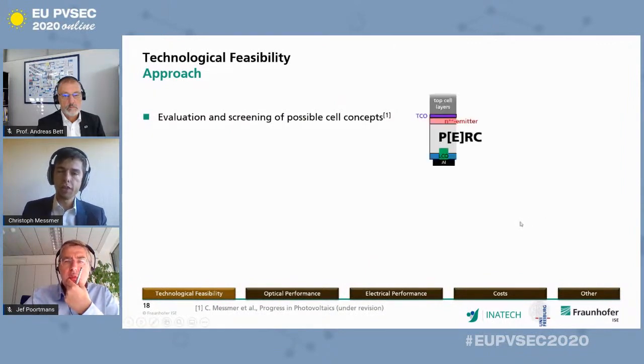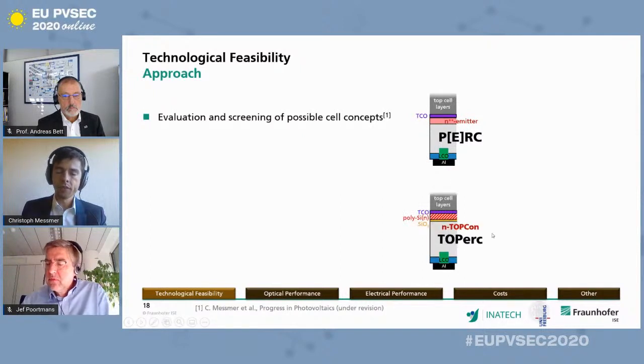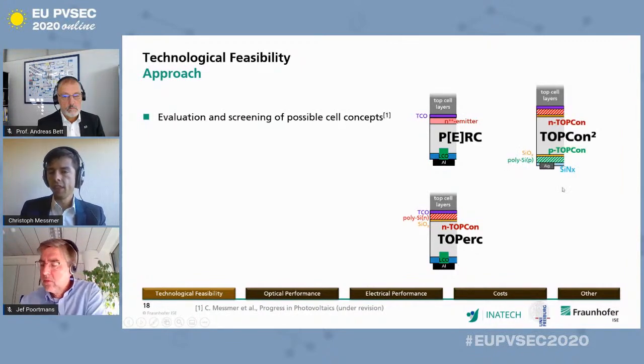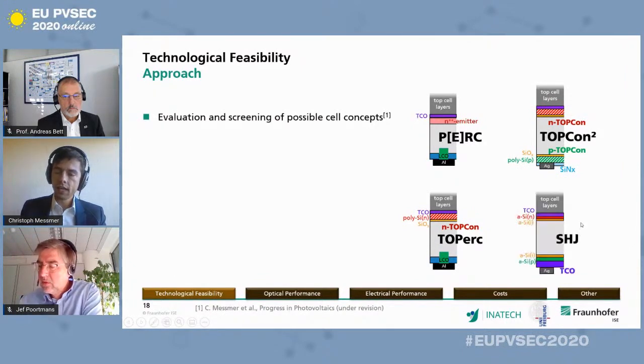And we ended up with, first of all, a PERC-like bottom cell where we have a PERC rear side and an unpassivated phosphorus diffused front emitter, which is then connected to the top cell layers. Secondly, a concept we call top PERC, since it has TOPCon on the front side and a PERC rear side. Then a TOPCon squared, where we have n-TOPCon on the front and p-TOPCon on the rear side. And finally, also the silicon heterojunction with the amorphous silicon contacts.